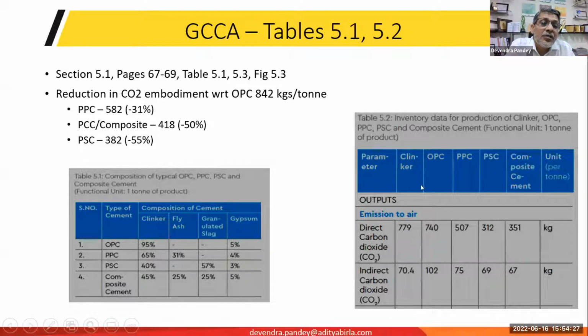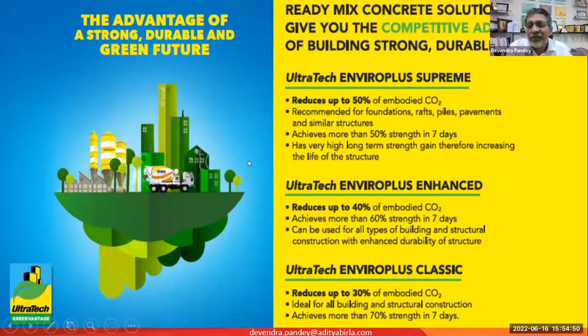Regarding the carbon footprint, this is where OPC is at about 740 kgs per metric ton, while PPC is at 507, slag cement is at 312, and composite cement is at 351. So this is when you directly use the cement, making the choice of cement. But when you are designing a concrete mix, you have a little bit more liberty, or your ready-mix supplier has a lot more liberty in tweaking the mix and targeting a certain percentage reduction in the carbon footprint of the concrete itself. So I'm just showing you here 3 categories of concrete products which have 30%, 40%, and 50% reduction in CO2.